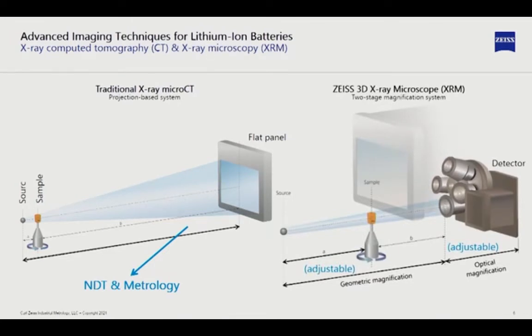But it's very difficult to go down to a submicron level, unless you use a different type of system that we call X-ray microscopes. The difference between the X-ray microscopes and the traditional X-ray CT is that these systems, in addition to the geometrical magnification, have an optical magnification added with a series of optical lenses. So you have a combination of two magnifications that increase the resolution capabilities. And that's how we can go down to nanometer resolutions.